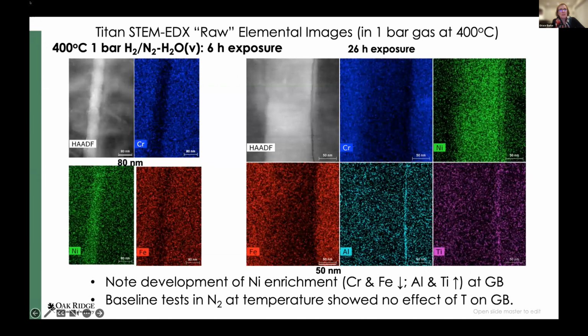And here I'm just going to show you what the exposures were like at 400 Celsius under 1 atmosphere, 1 bar gas. After 6 hours, in our HAADF image, we can see that we have chromium depletion, nickel enrichment, a little iron depletion as well. And then after 26 hours at temperature, the chromium depletion has expanded, nickel enrichment has expanded, and we can see a linear trace of titanium and aluminum. Now, I want to point out as well that these are raw data. These are not processed. This is as collected. The reason being that we're looking through our silicon nitride windows. We're also at a 5 micron gap. We have gas in there, and we're just showing you the raw data.